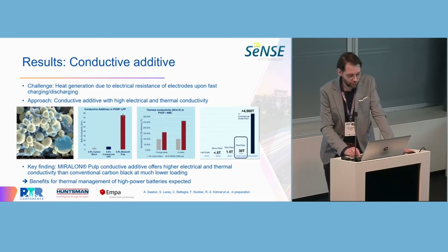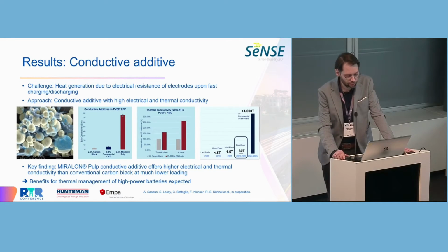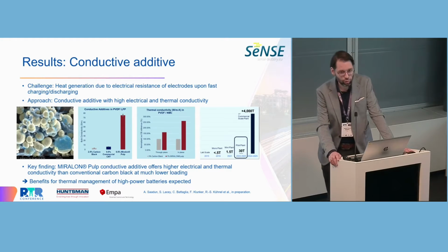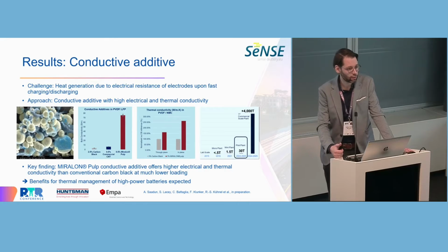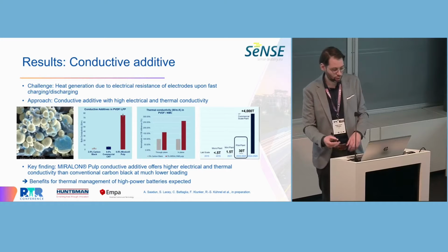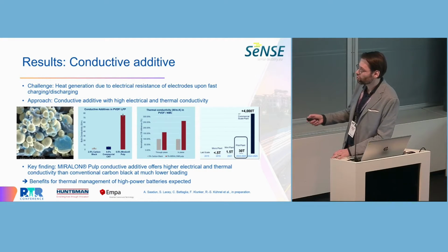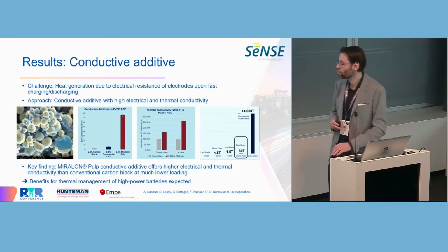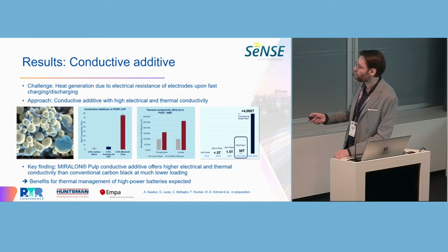When you are at these high energy densities and also for fast charging, heat generation and also heat dissipation are becoming more important. And here our approach was to substitute the standard or conventional conductive additive carbon black by a carbon nanotube based conductive additive with significantly higher electrical and thermal conductivity. So here you can see an SEM image of an electrode. It also nicely wraps around the particles, and we were really able to significantly increase the electrical conductivity compared to the conventional carbon black based approach, and also the thermal conductivity.